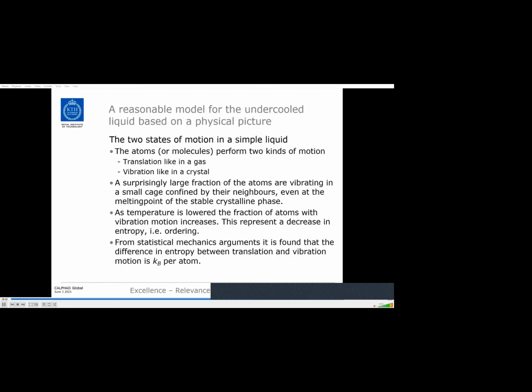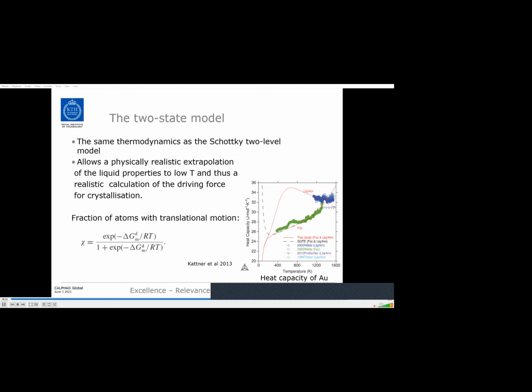As temperature is lower, the fraction of atoms with the vibration motion increases, and this is represented by a decrease in the entropy, that is, an ordering. And from statistical mechanics arguments, we can find that the difference in entropy between translational and vibrational motion is k Boltzmann per atom. So this led to the two-state model, and it gives the same thermodynamics as the Schottky two-level model, and it allows a physically realistic extrapolation of the liquid properties to low temperature, and thus a realistic calculation of the driving force for crystallization. So in fact, we can derive this kind of expression for the fraction of atoms with translational motion.